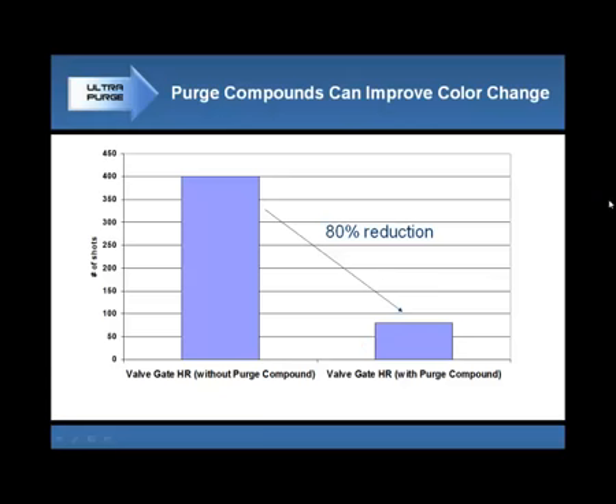Also, using purging compound is extremely important. Purging compound is normally proven to drastically reduce scrap and downtime. For example, in that particular case, the two slides above, the same color changes performed with UltraPurge give a reduction of 80% in scrap alone, which is definitely a huge saving.